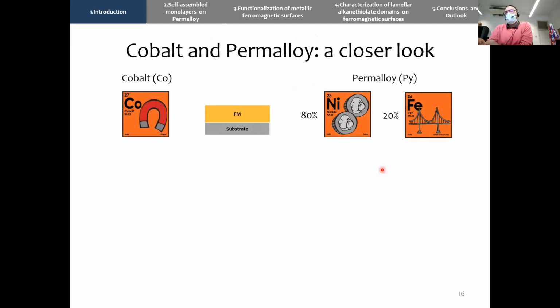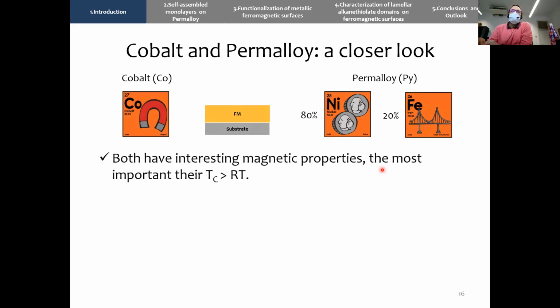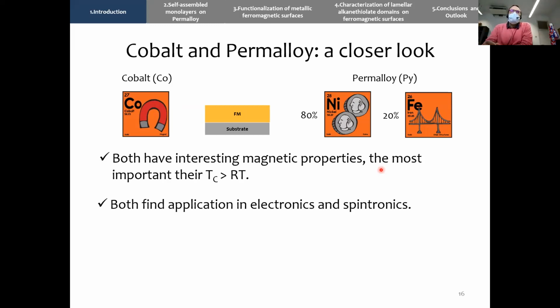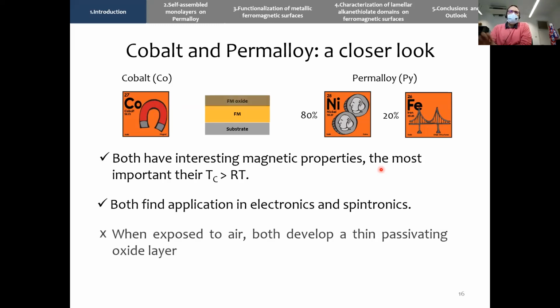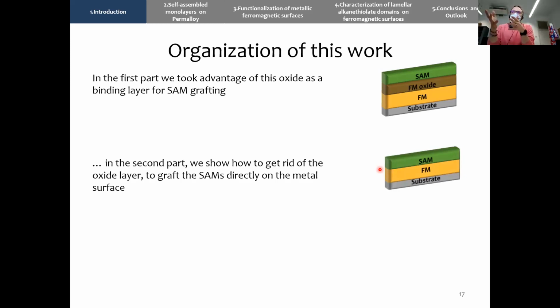Permalloy is a nickel iron alloy made of 80% and 20%. Their Curie temperature is well above room temperature, so they are magnetic at room temperature. They are already used in electronics, and so their transition to spintronics should occur easily. The problem is that they tend to oxidize when they are exposed to air. So in the first part, I will show you how we use this oxide as a growing platform for SAMs. In the second part, how we get rid of this oxide.